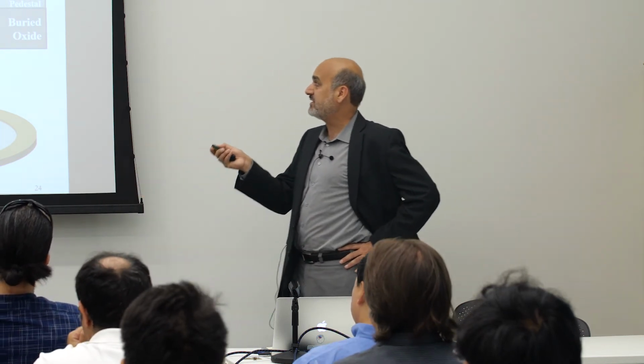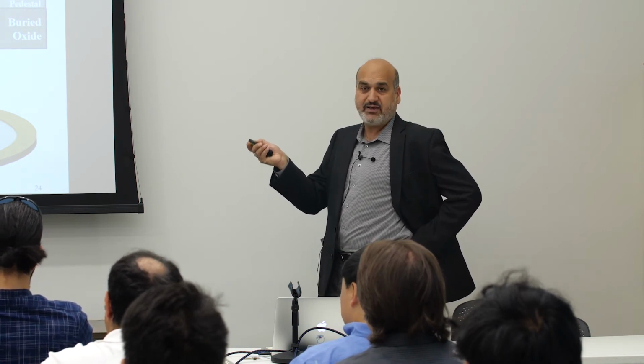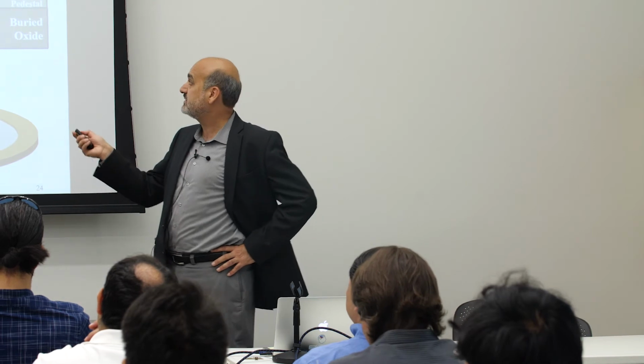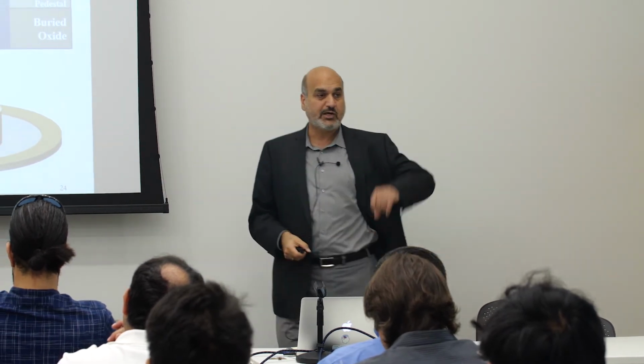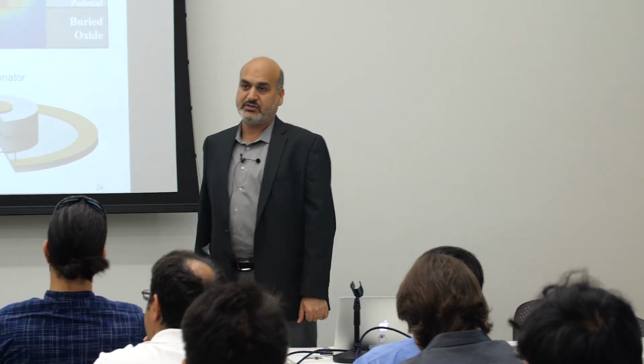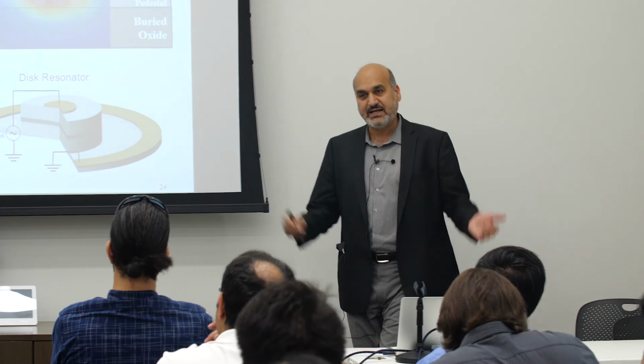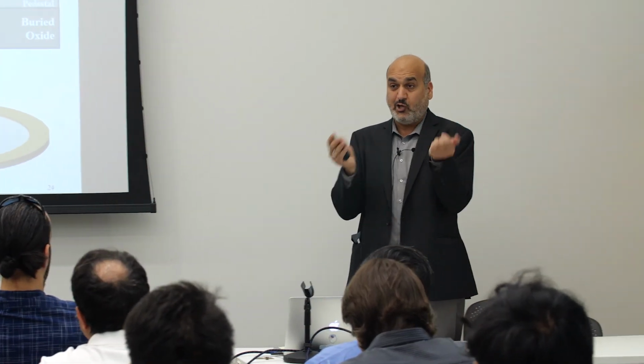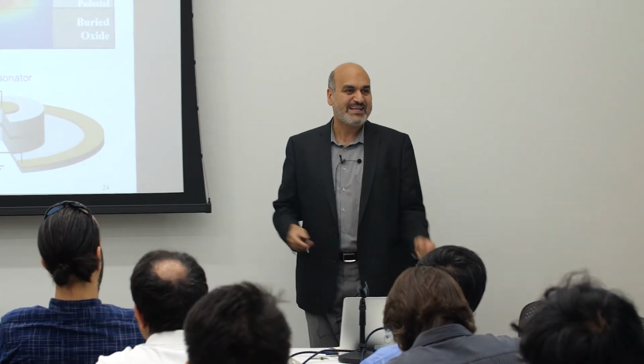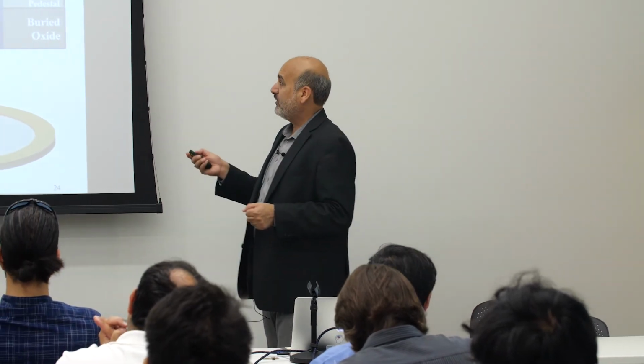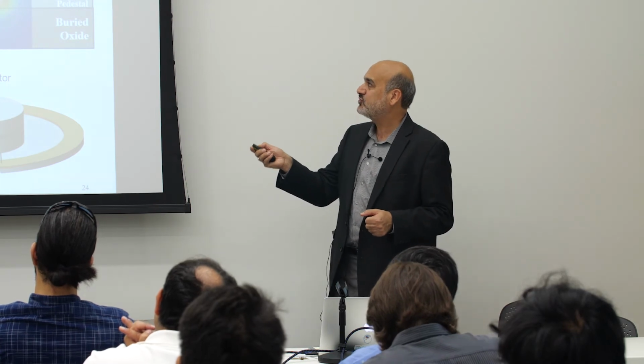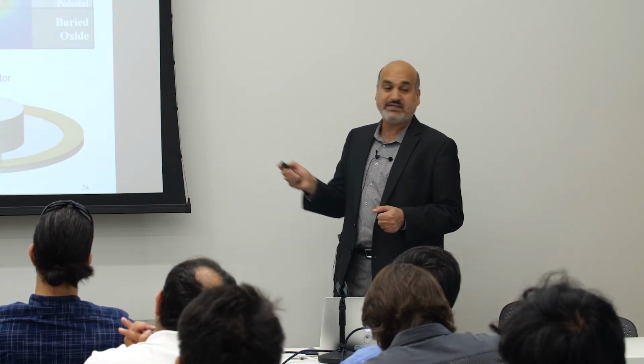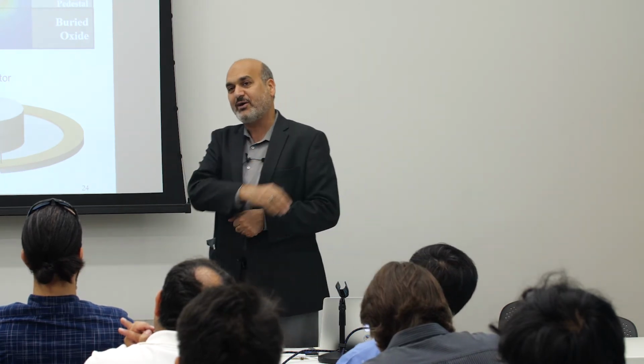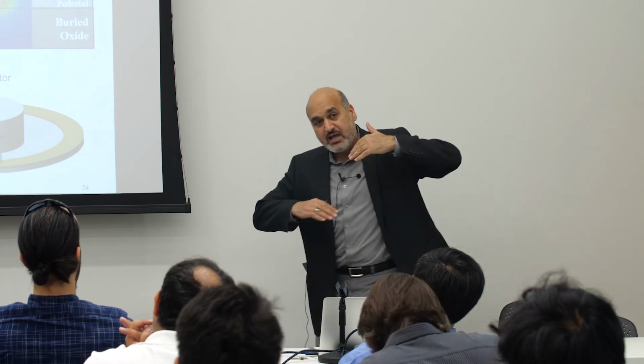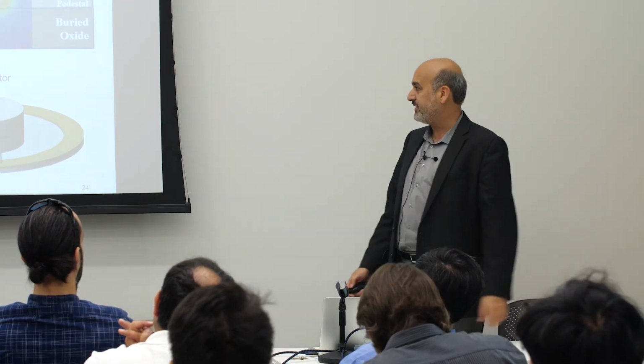And then there are a lot of games that we can play, because now the capacitance here defines the voltage of operation, because you need so much charge to be accumulated. The larger the capacitance is, the smaller the voltage is. Q equals C times V. But at the same time, when capacitance is large, your speed is sacrificed, because the RC time constant is your speed. So these are the types of trade-offs that we deal with in this technology. And just to move ahead of myself, eventually, if we use a very low resistivity material like graphene, then I wouldn't worry about resistance, and I can play just with the capacitance. So that's a trend that it opens up as a new hybrid material platform.